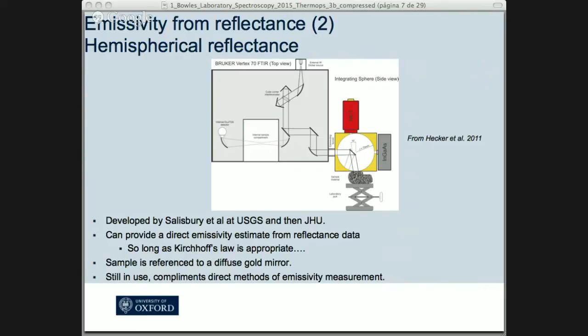And you have these, this is from Hecker et al., and sensors, I think, but this is a pretty standard setup. You have your detectors on the sides of it, they're plugged in, and then you pick up the diffusely reflected radiation. And if you put a little motorized flip mirror in here, you can then do a bit of self-calibration internally by looking at the diffuse sides of the wall of the integrating sphere.